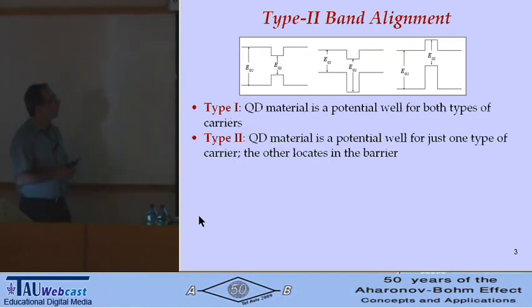Type 2 band alignment: if you have two heterostructures, let's say quantum dots, in a semiconductor, you can have basically two types of band alignment. One, when the material of the quantum dot with a smaller band gap is completely within the band gap of the material with a larger band gap, we call it type 1. That means the electron and hole will be confined within the quantum dot, so spatially they will be sitting in one region. But then you can have a situation when, let's say, the conduction band of the quantum dot material is below the conduction band of the barrier material, but the valence band is also below the valence band of the barrier material, and the same for electrons.